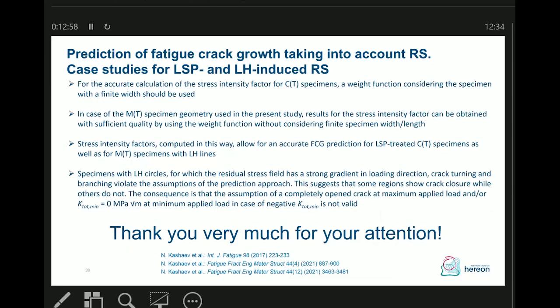Next slide, and here is the summary of my talk. In principle, I have shown you that the weight function method is a very powerful tool for predicting the fatigue crack growth rate in specimens with induced residual stresses. And one important aspect, of course, is that you have to consider the limitation of the method if we have an additional retardation effect due to non-straightforward propagation of the crack. For such cases, the weight function method is not applicable.